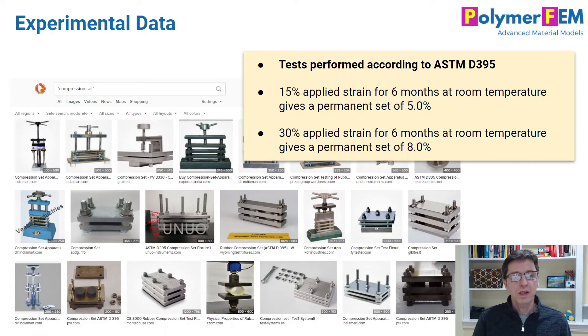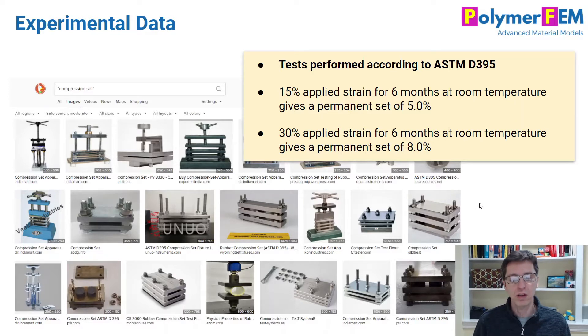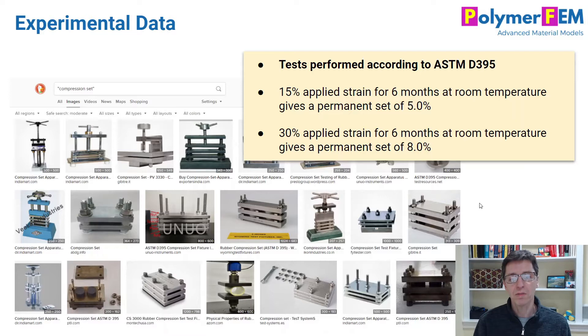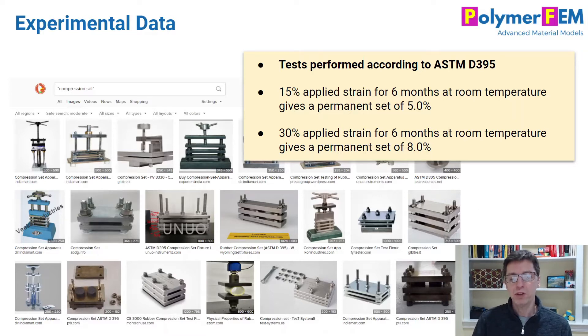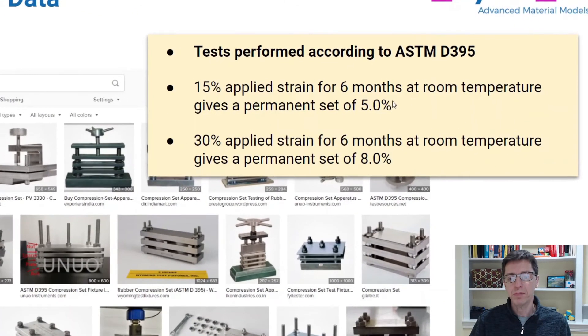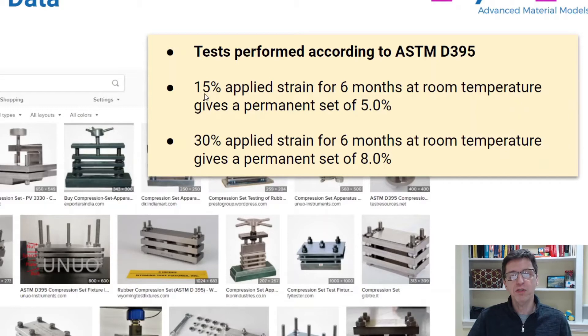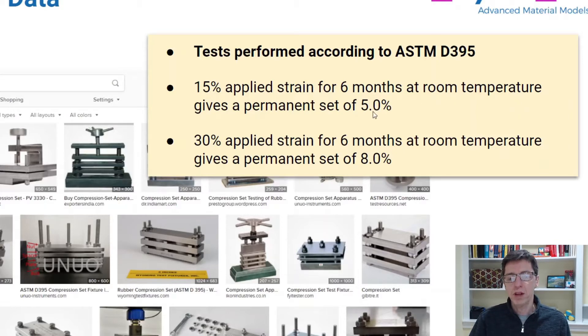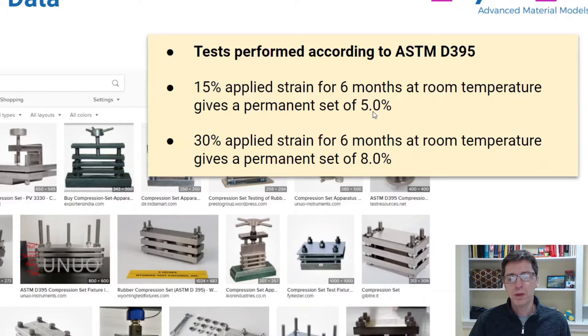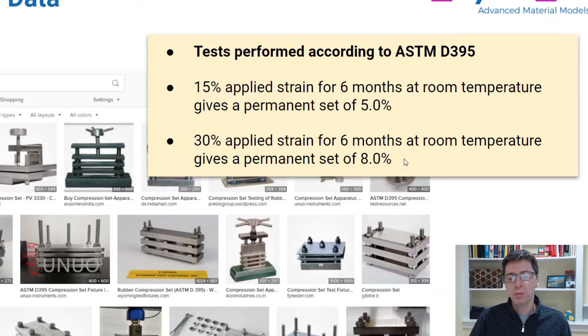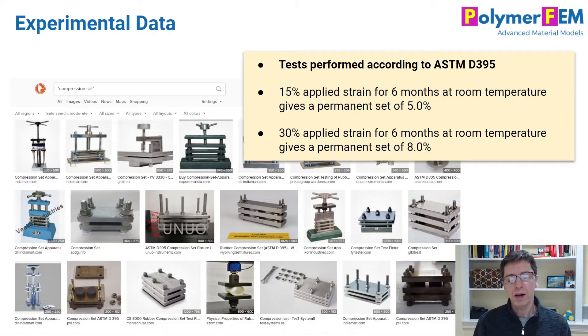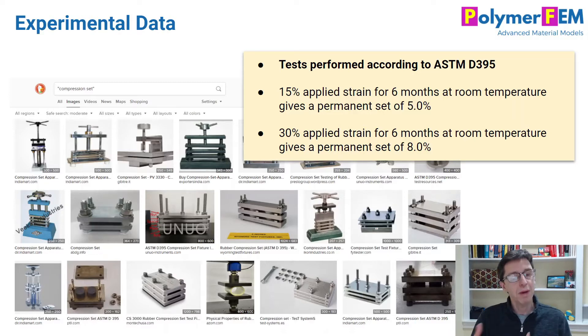And then you look at the final dimensions to look at how much they actually have changed the dimensions due to this exposure, the compression set that is. And if you do a quick search for compression set, you'll see that there are tons of companies selling these fixtures. You can make your own very easily. As you can see, they're very basic tests. So in this case, for the example I'm looking at, we have the uniaxial compression test at three strain rates. But I also performed permanent set experiments. In one test, I compressed the rubber specimen 15% and I held it there for six months at room temperature. And after the test, we had a 5% permanent set of this rubber. And that test, I compressed it to 30% strain. I held that for six months and that gave me a permanent set of 8%. So those numbers are really important to know when you're trying to come up with a good material model that can match this data.